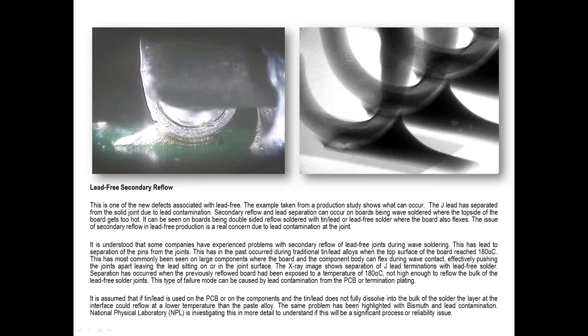Now, something that we have seen and still continue to see periodically is secondary reflow. And there are two forms of secondary reflow. One where you have already reflowed a product and do side two, and the temperature you're using causes the solder joints to reflow again. And because you might have flexure of the board or the pallet supporting the board, you might get some open joints. So that's sort of typical secondary reflow. Or you're reflow soldering and then you're wave soldering that product or selectively soldering that product, and you don't control your top side board temperature. If the board warps, you get open solder joints.